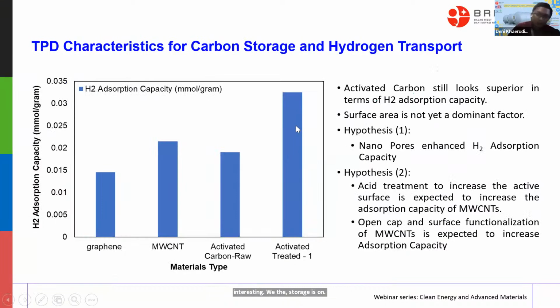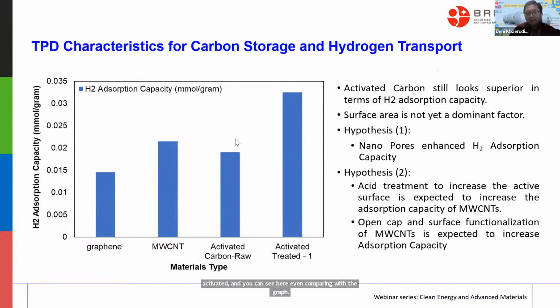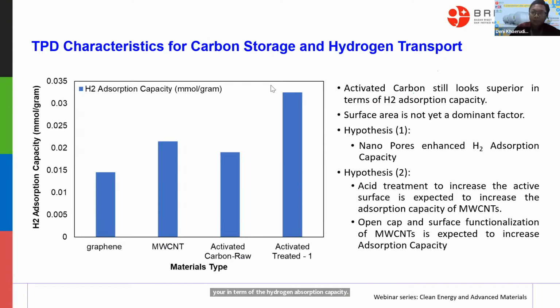Okay, this is our data, but actually we cannot show it, just slightly. Here, we compare graphene, multi-wall carbon nanotube, activated carbon, and treated activated carbon. And you can see here, even compared with graphene, the activated carbon is superior in terms of hydrogen adsorption capacity. Please remember, this is just chemisorption testing, the H2 TPD that we already tested here. But this is not representative of